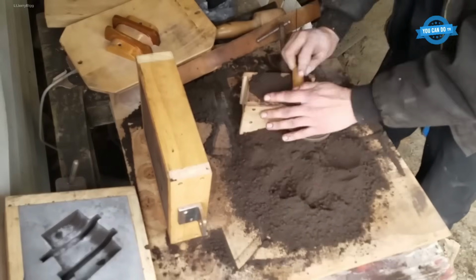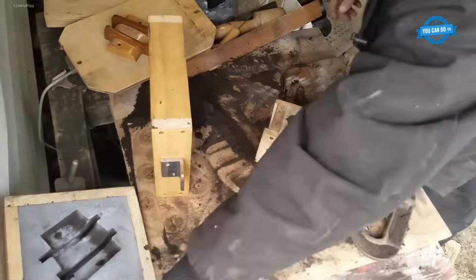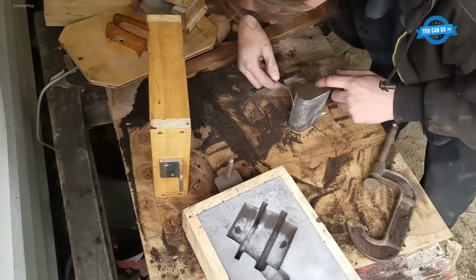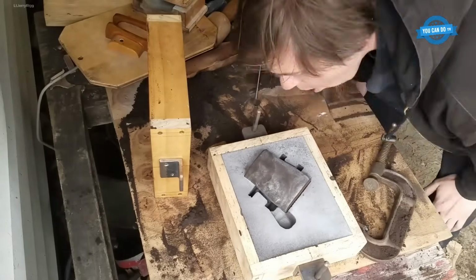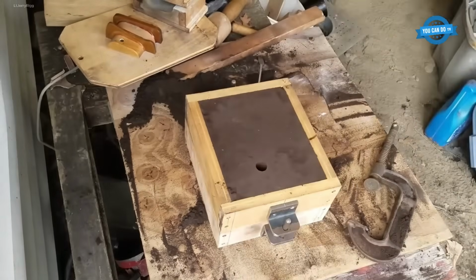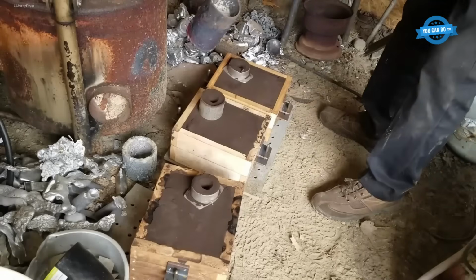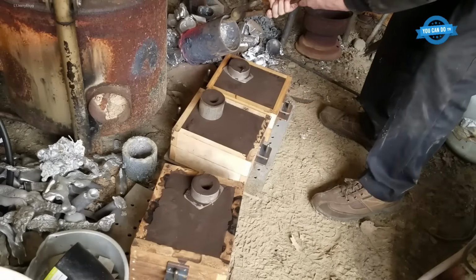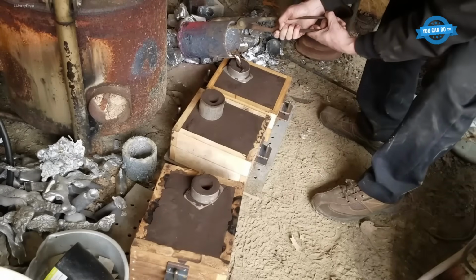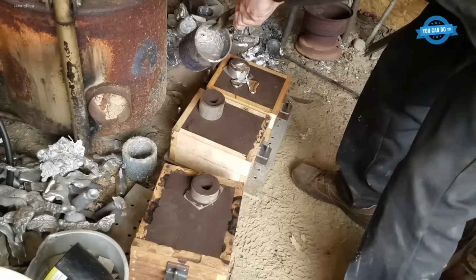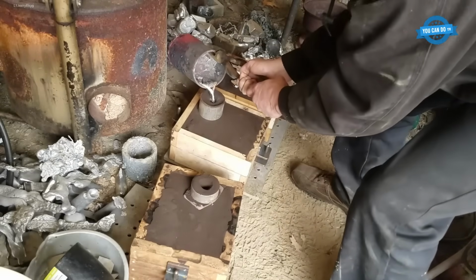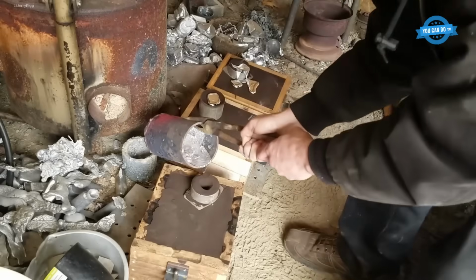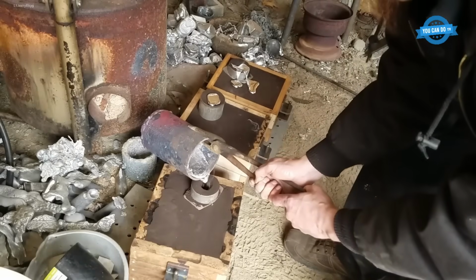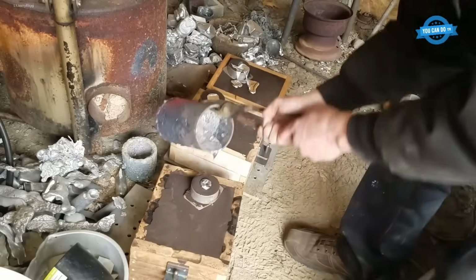Molten aluminum, heated to over 700 degrees Celsius, is poured into the mold cavity. As the metal fills the void, risers compensate for volume reduction during solidification, ensuring the casting remains free of internal voids. After cooling, the sand mold is broken apart and the raw casting is removed. Risers and excess flash are trimmed off, and the casting undergoes shot blasting to remove scale and provide a uniform surface.